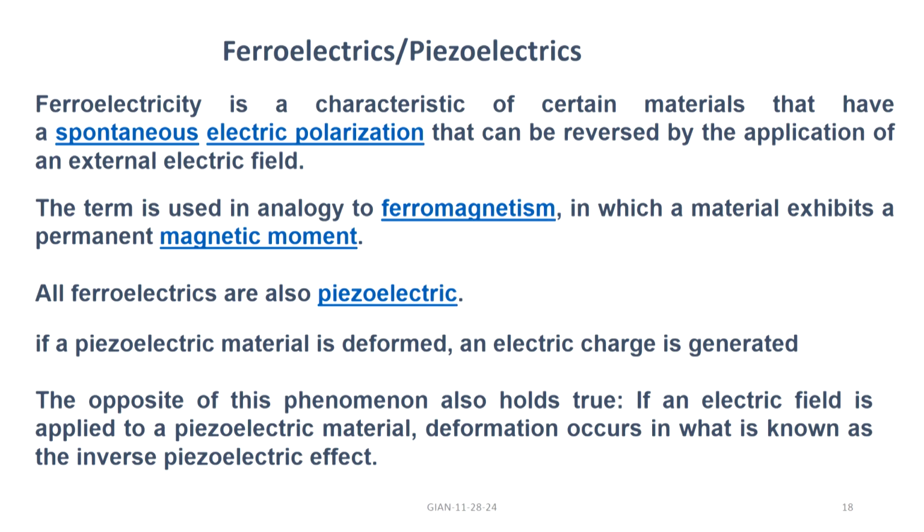In a ferroelectric, similar to a ferromagnet, where there is spontaneous magnetization, you have spontaneous electric polarization, and that can only be reversed if you apply an electric field, similar to the case of a ferromagnet, where you cannot reverse the magnetization direction unless you apply an external magnetic field, and it takes energy to either reverse the polarization or realign the ferroelectric domains in the ferroelectric.